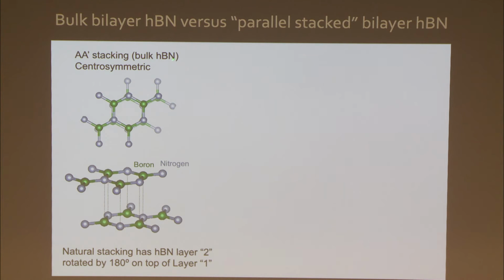So bulk bilayer hexagonal boron nitride has AA prime stacking. It also has these AB atoms, like graphene, but now they're actually different atoms, boron and nitrogen. That breaking of the symmetry makes it a wide bandgap insulator. And the natural stacking in the bulk is AA prime. Boron and nitrogen alternate on top of each other. The bilayer case is a centrosymmetric material. It's not a ferroelectric, it's not polar, nothing, okay? The natural stacking means that layer number 2 is rotated by 180 degrees on top of layer number 1.